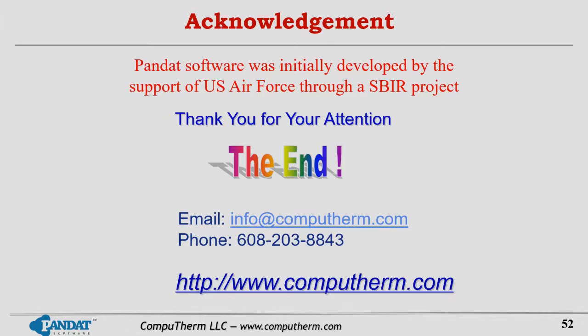If and how do you handle any uncertainty for the alloys where all the ternaries are not available in the thermodynamic database? Yeah, that's a very good question. For ternary systems, if we do not have enough experimental data, sometimes we need to do some ab initio calculation, first principle calculation, to get some ballpark about the energy at different areas, different compositions. Then we can use that information to develop the database for the ternary system that has no enough information. Certainly, sometimes we need some experimental data to validate.